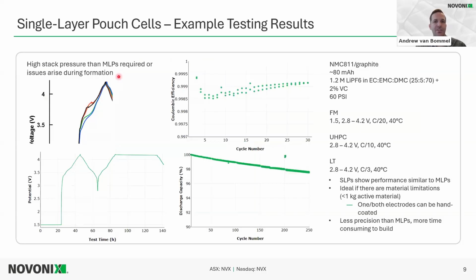So here's some example testing results. When we first started testing some of our single layer pouches, here's some formation data. I just did a zoom in here of some of the formation data initially, and we found that with normal stack pressure, we had a strange bump on formation on that charge profile. And we figured out that that bump was due to possible formation gases being trapped in pore wetting on the electrodes. And so we were able to get rid of this by pushing out the formation gas in a way by increasing the pressure even higher than our stack pressure for multi-layer pouches.